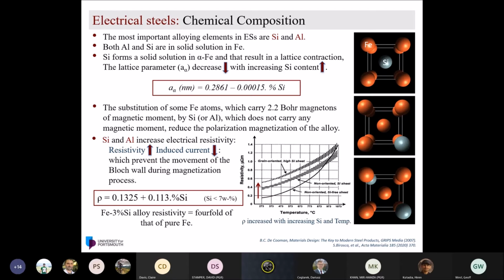The reason you add silicon is that if we substitute an iron atom with silicon, the iron atom carries 2.2 Bohr magnetons of magnetic moment, while silicon and aluminum don't carry any. So you are reducing the polarization of the alloy, and hence increasing the resistivity of the alloy to reduce the eddy current in the metal, and that is what prevents the movement of the Bloch wall during the magnetization process.